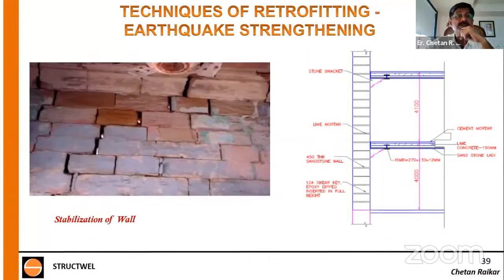This is how all the stone walls were. This is a 450 mm thick wall, and there were walls of 600 and 750 also. You can see in the left photograph, you can see the daylight through the entire width. So this crack is through. What you see here is a through crack formed by an earthquake. So now how do we restore such a crack? What we did was fill the cracks first, grouted them, and then